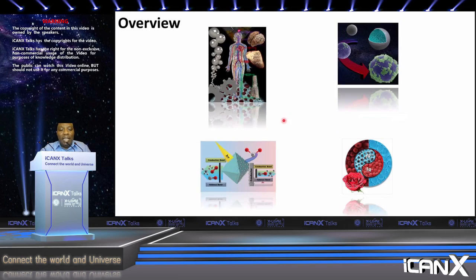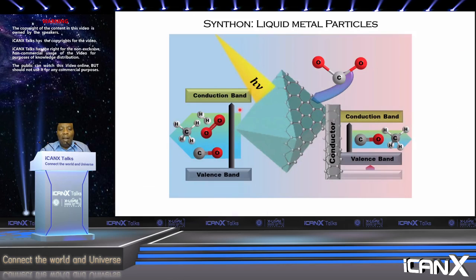And finally, the last story I wanted to share with you is related to how we can actually now tap into that oxide and ask the question, can we make new materials that actually will perform in a very different way than what we would expect? And here, we decided to exploit the fact that we can etch the oxide, form components on the surface, organometallics, and then assemble them to make high aspect ratio nanomaterials, and then take those materials and make them into graphene or graphite-covered metal oxides.